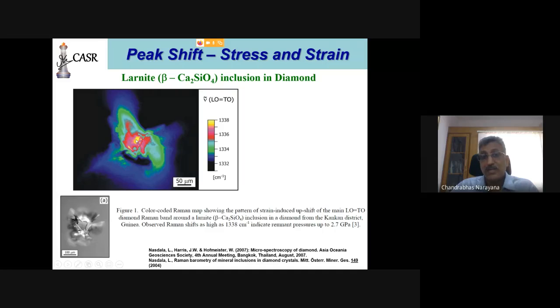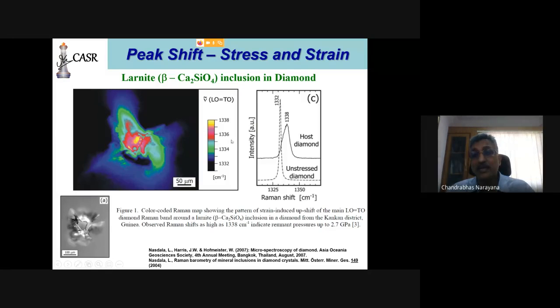Now, 1332 to 1338 is because if your spring constant is increased, that means you are compressing the system. When you compress the system, you can actually increase the spring constant. That means you are bringing the atoms closer. How do you bring them closer? You can do a pressure study. So you can see that if you apply pressure on diamond, it can shift from 1332 to 1338.